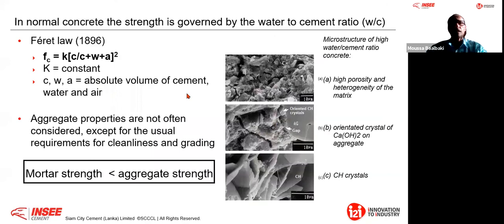Now, in normal concrete, in this slide, what is written here you know very well: the strength is governed by the Féret law or the Abrams law, that is the water cement ratio. I'm not going to tell you more because you know very well that if I increase my water cement ratio, my strength will go down in normal concrete. Therefore, it's very important to keep in mind that we don't often have a problem with the aggregate, because aggregate properties are not often considered, except, of course, requirements regarding cleanness and grading.